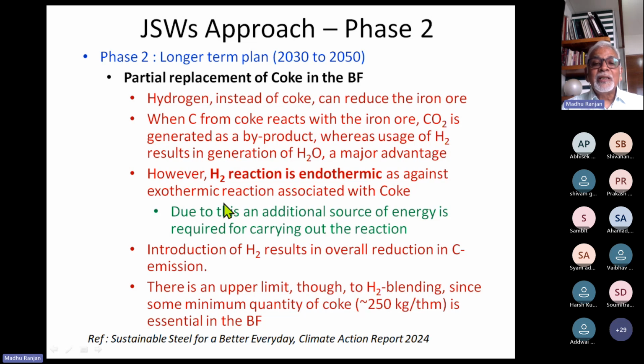But there is a catch here. The hydrogen reaction is endothermic as against the exothermic reaction associated with coke. Therefore, to use hydrogen, you need an alternative source of energy as well. So introduction of hydrogen results in overall reduction in carbon emissions. There is an upper limit, though, to hydrogen blending, since a minimum quantity of coke, that is 250 kg per ton of hot metal, is essential to run the blast furnace.